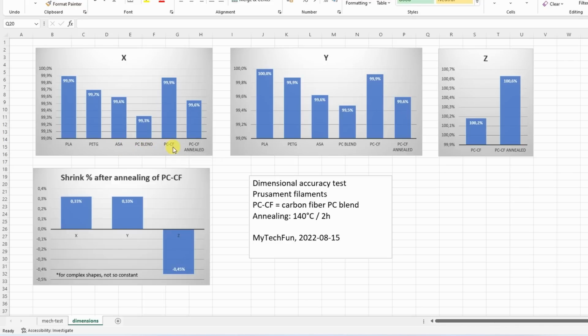And with the carbon fiber version of the PC blend, I get almost the same accuracy in the dimension as with the PLA. And this is the shrinking of the carbon fiber filament after the annealing. And very similar values I got with the y-axis. Now in the Z direction, I measured only the carbon fiber and annealed carbon fiber. And here I actually experienced that after the annealing in Z direction, the dimension expands.